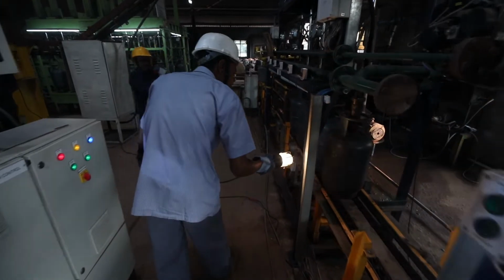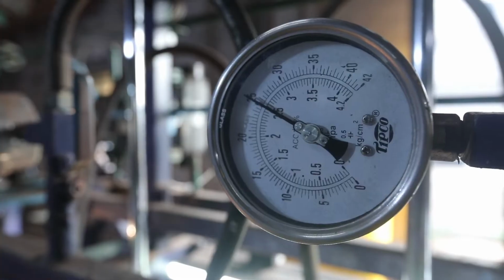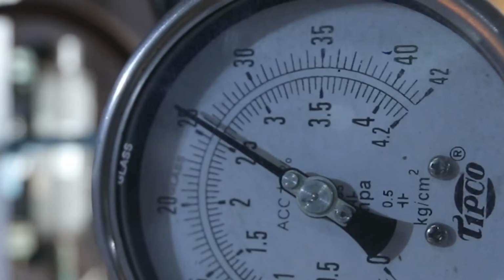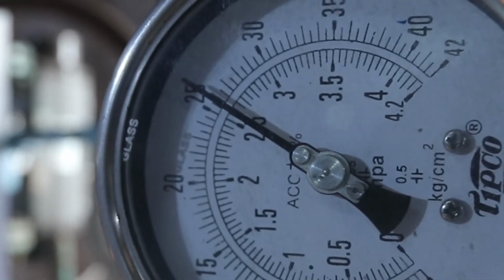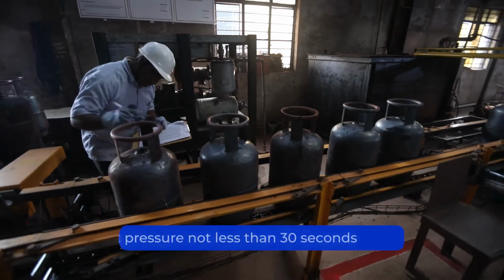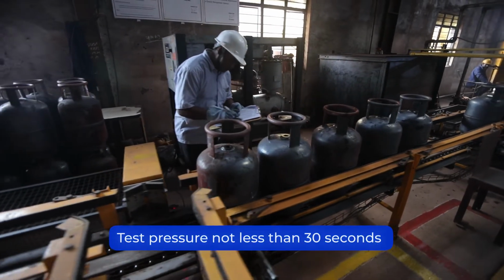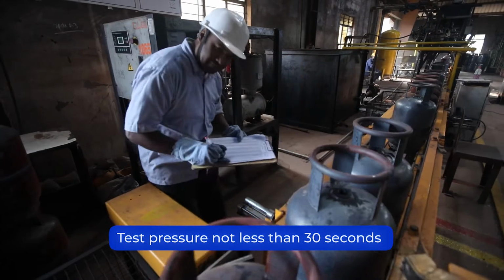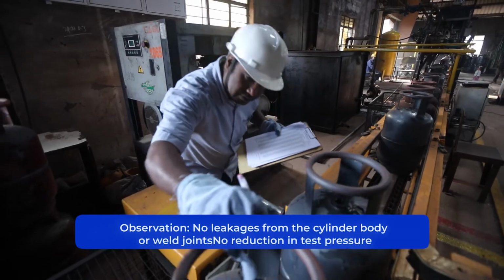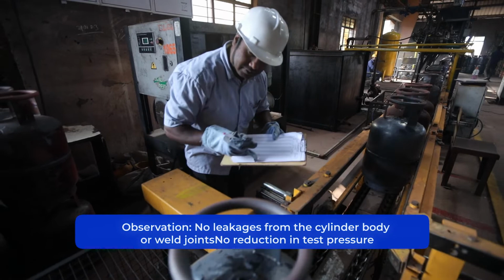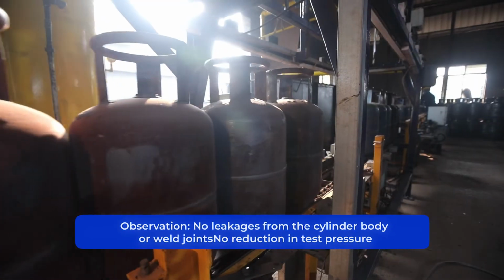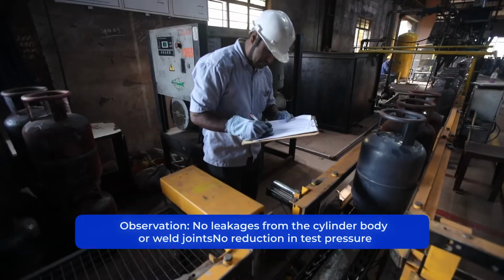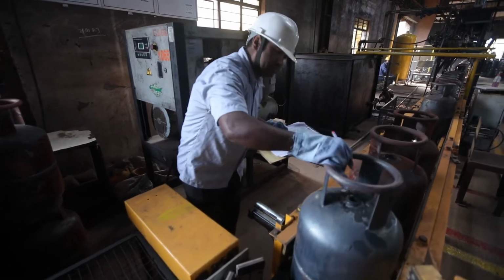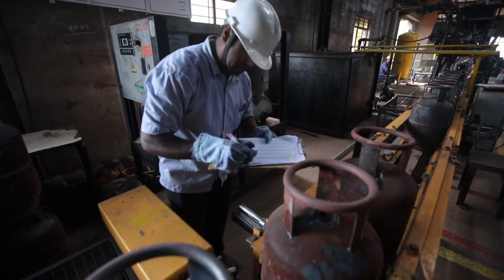For the hydrostatic test parameters, the test pressure should be 25 kg force per square centimeter. Test duration under the test pressure should not be less than 30 seconds. There should be no leak from the cylinder body or weld joints. Also, no reduction in the test pressure. Please note that the test results will always be recorded.